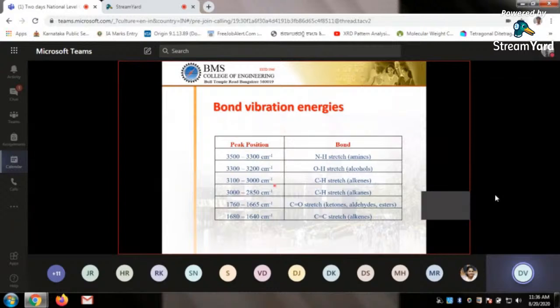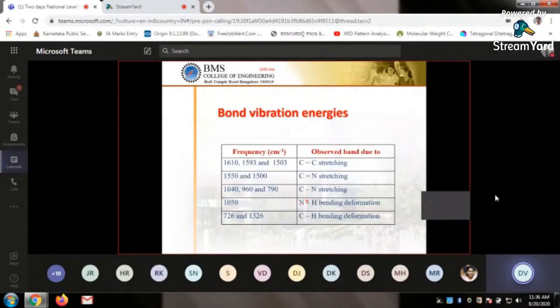Coming to FTIR, these are standard vibration peaks. We can assign single bands or double bands by taking your sample and analyzing the position of the peaks. This is an example of pure polypyrrole. Here we observed these peaks, which are due to C=C stretching, and this frequency is due to C=N stretching. Like that, you can assign each bending or stretching deformation for your samples using Fourier transform infrared spectroscopy.